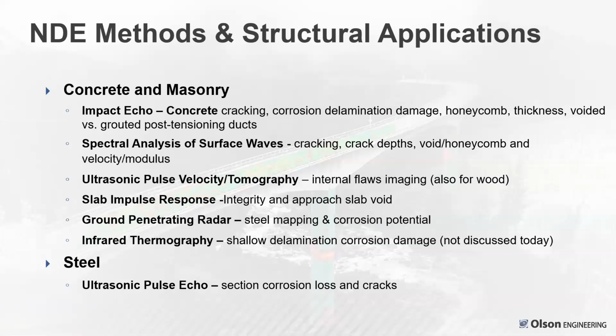So the methods and structural applications for concrete and masonry in particular are impact echo, finding concrete cracking, corrosion damage, delamination, honeycomb, thickness, voided versus grouted post-tensioning ducts. Surface waves can be used for cracking, crack depths, perpendicular crack depths in particular, void, honeycomb and the velocity and modulus of the material. Both of those tests are one-sided access tests.